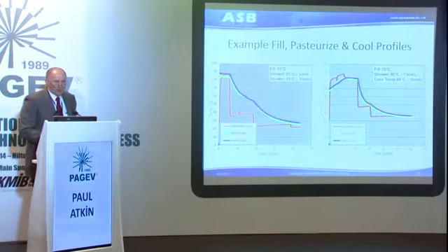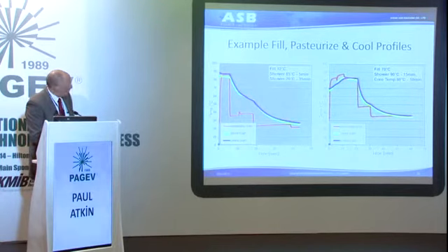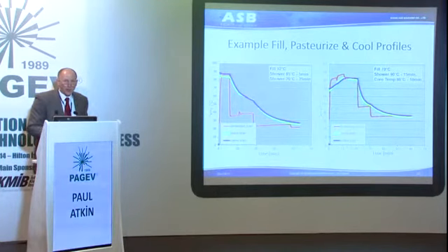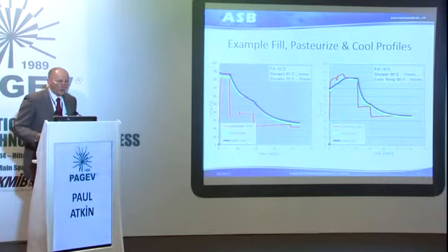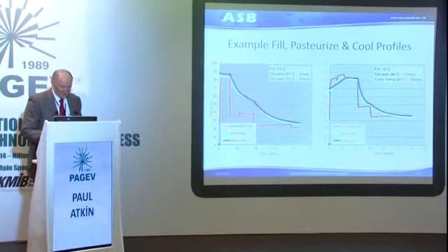Here are some examples of the type of temperature profile we may see. On the left, we hold at high temperature for a few minutes, then immediately start cooling. On the right here, the product is filled much cooler at around 70 degrees C, and then is actually heated up and held at 80 degrees C for 10 minutes before cooling starts. And again, it just depends on the foodstuff which is going into the container.